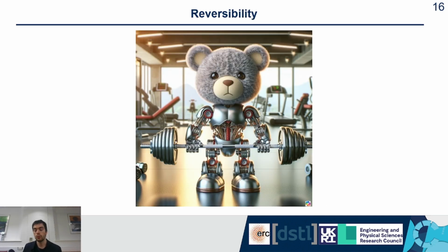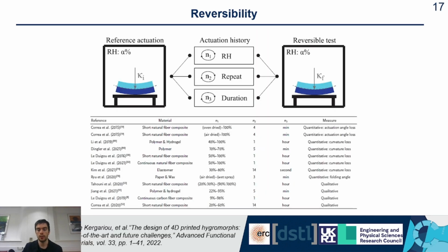So that lovely soft robot wants to do reps at the gym, and so he wants to know how many he can do so that you obtain the same motion for the same solicitation, for the same humidity, basically. And in order to do this, you need to test the reversibility of the material. So we define in our literature review the reversibility as a 3-step process in which you have the reference actuation. So you condition your actuators in a specific humidity, let's say alpha %. You measure its actuation, so let's say kappa I, which is the initial curvature, and you give it an actuation history, which is conditioning your specimen for N1 relative humidity, or N2 repeats during N3 days, weeks, hours, whatever you want. Then you condition it back to the initial relative humidity, alpha %. You measure its deformation again, and you compare kappa F to kappa I in order to know if your material is reversible or not.